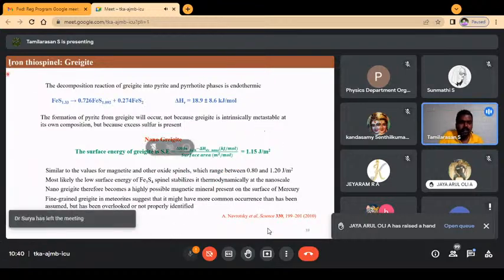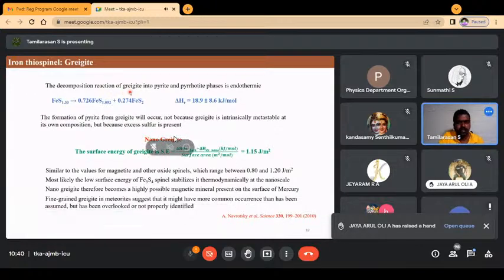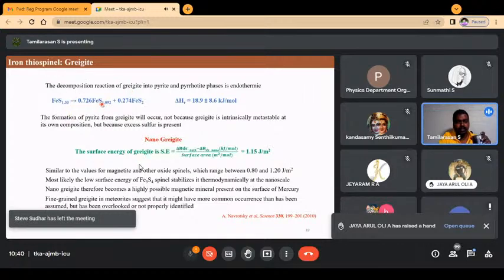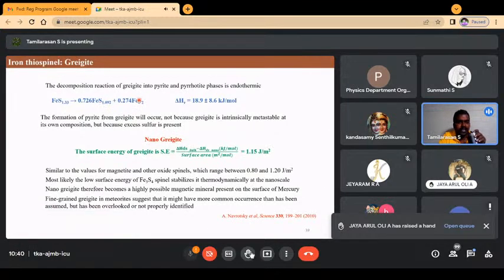And also we found that in the phase assemblage of the iron sulfide phase diagram, greigite is stable with respect to decomposing into its neighboring phase compositions like pyrrhotite or pyrite, and so we revealed that it's indeed a stable compound.